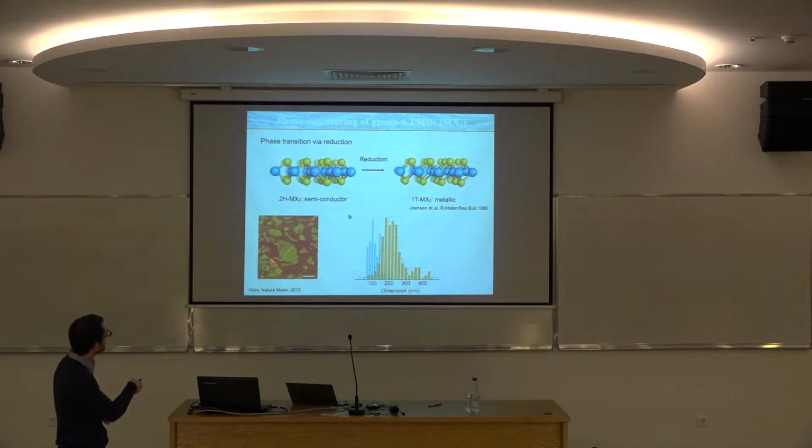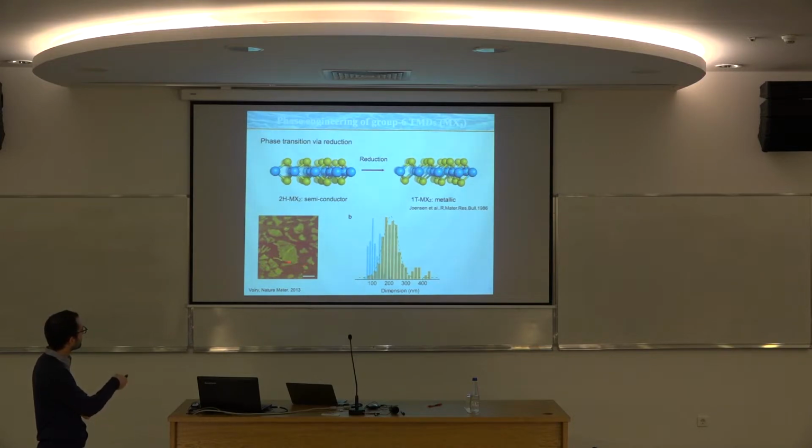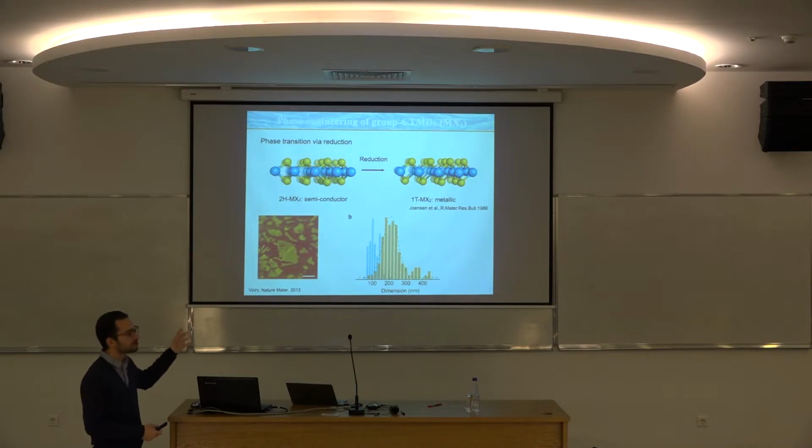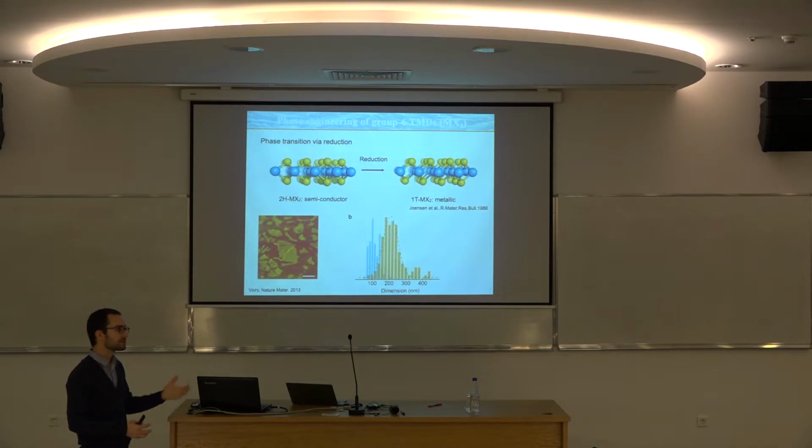So the typical image of these nanosheets is shown here. This is an AFM, atomic force microscopy, image of a deposit of MoS2 nanosheets on a silicon dioxide wafer. In yellow, you have these nanosheets. The color contrast comes from the height of the sample. The brown region is just the substrate, and the yellowish is the nanosheets. So you see it's roughly the same contrast, which tells you this is the same thickness. The thickness here is about 1 to 1.2 nanometer,